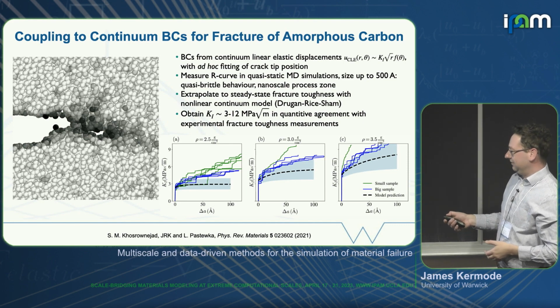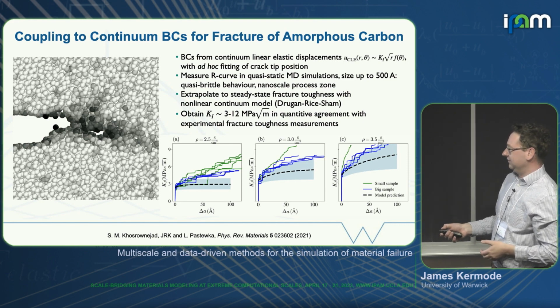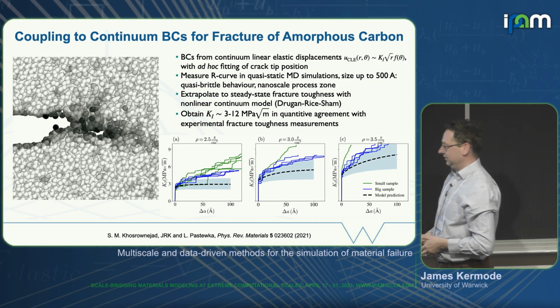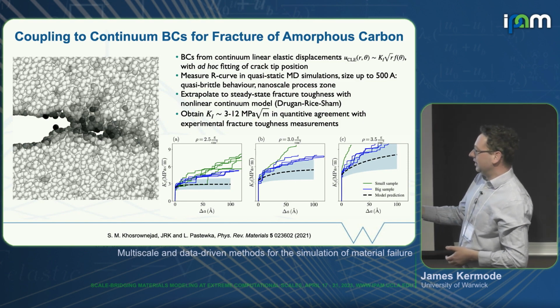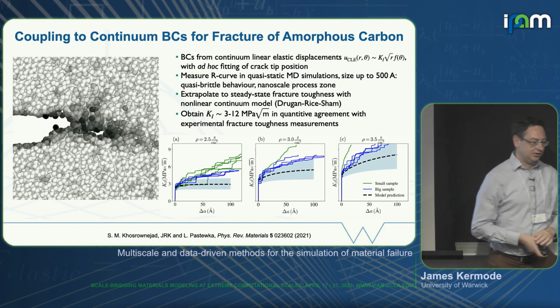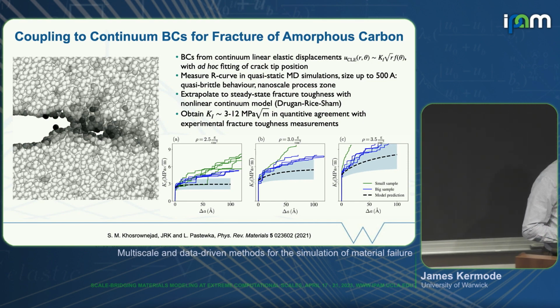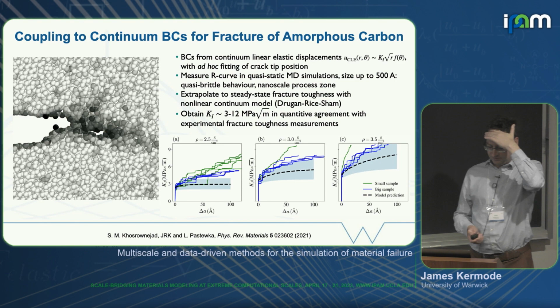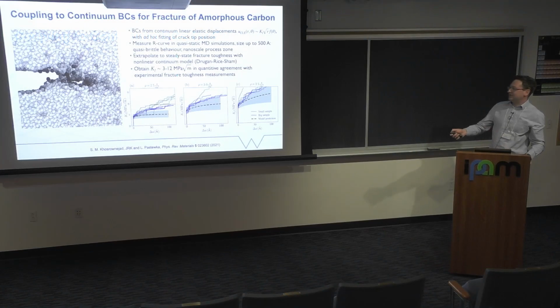So by varying the density of the specimen, by looking at different sizes of sample, and by extrapolating to large samples, we can come up with a range of stress intensity factors that agree pretty well with known experimental measurements for amorphous carbon. But as I say, the unsatisfactory part, particularly from a mathematical point of view, is having to somehow determine where the crack tip is.